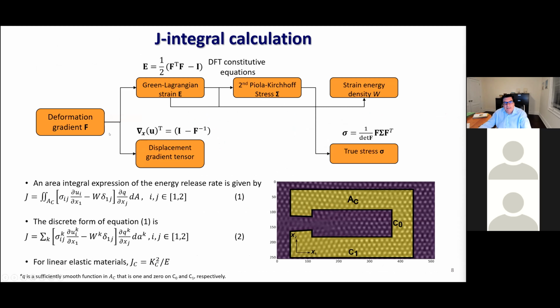The way we obtain that is, I told you how we compute the deformation gradient. From continuum mechanics, we can compute the Green Lagrangian strain, and using a density functional theory constitutive equation, we can obtain the second Piola-Kirchhoff stress. And again, from continuum mechanics, the Cauchy stress or true stress, and in addition, the strain energies. So that gives us the methodology to perform this experiment that I mentioned, and then map what is the toughness that is observed in that experiment.